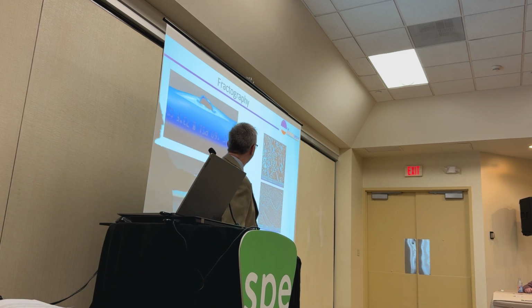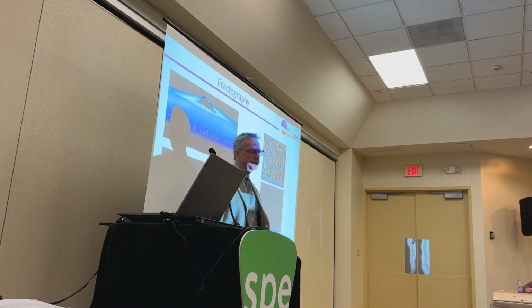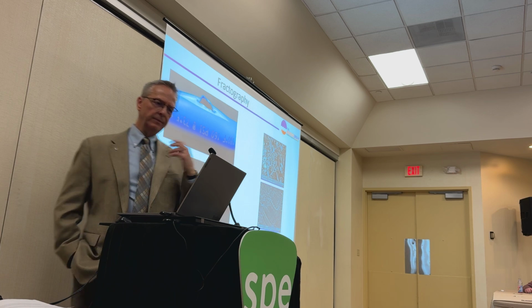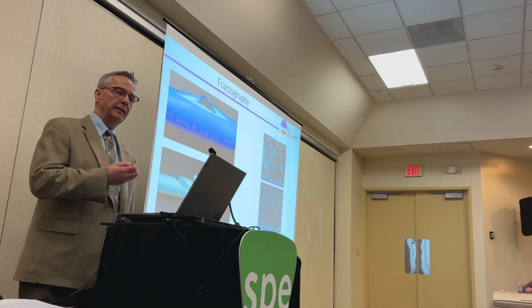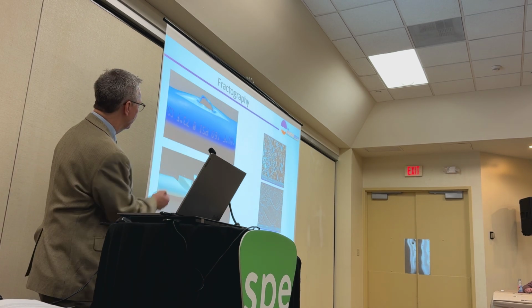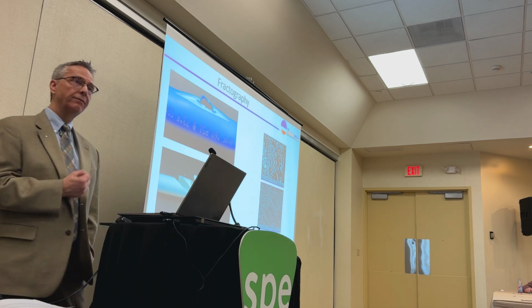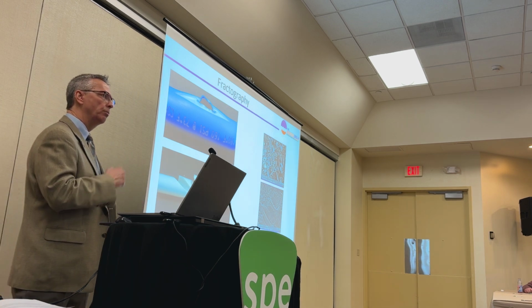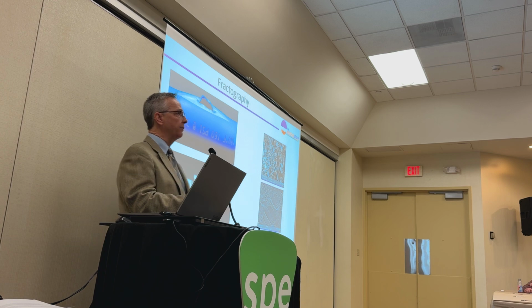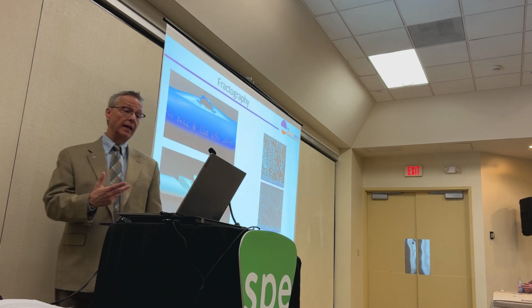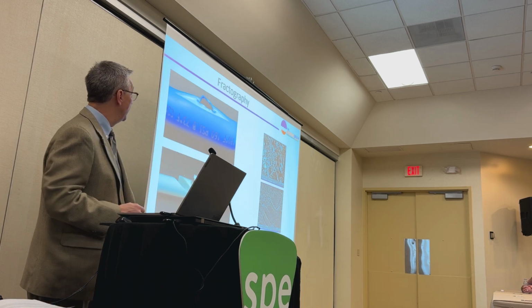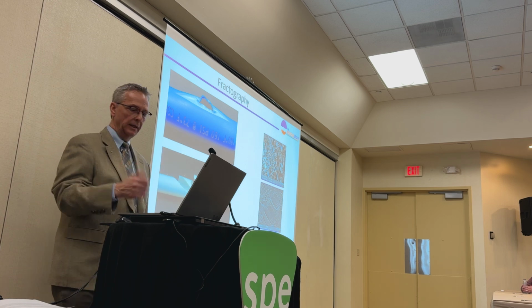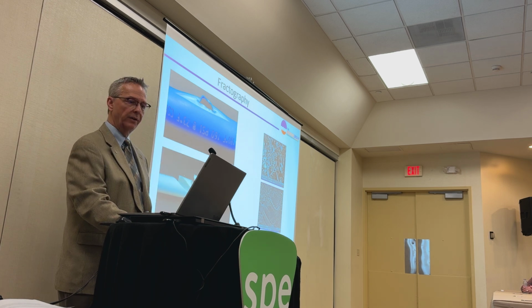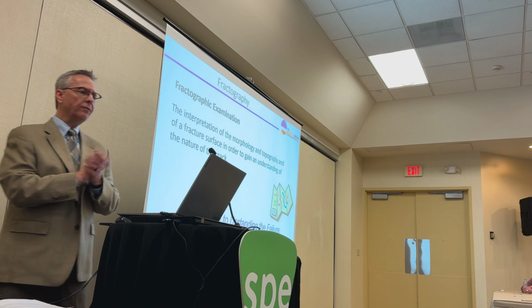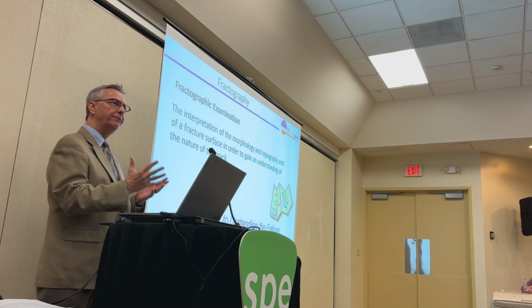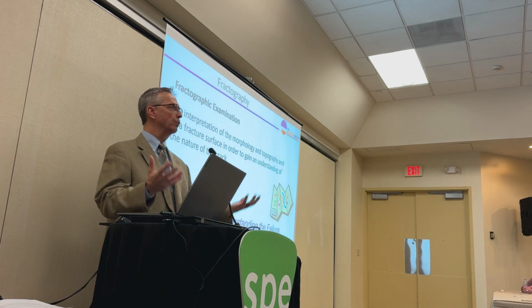From a micro perspective, when we're at higher magnification, the stretched fibrils we see in the upper image, that is ductility. And in the lower, we have a very planar, very flat fracture surface. That typically represents a more brittle fracture. Again, we could talk about fractography for a full day and still not get through everything. But that's kind of what I mean by macro and micro ductile or brittle fracture. So through our fractographic examination, we're going to read the features that we see on the fracture surface like a roadmap.